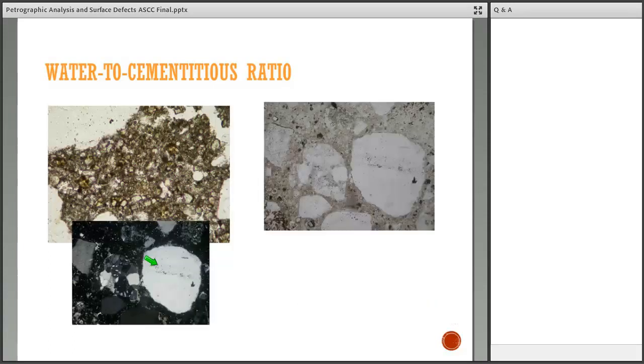Not only do we look at thin sections, because you can be fooled sometimes by thin sections, you also look at paste to aggregate bond when you hit it with a hammer. You look at the resulting fracture. Does it pass through or around aggregates or both? You look at the paste luster on the freshly fractured surface. You look at paste hardness. How easily can you scratch it with a dental pick?